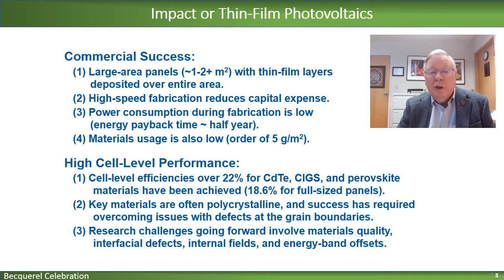At the cell level, we're talking about pretty high efficiencies. Over 22% has been achieved by cadmium telluride, by what we call CIGS, and by the class of perovskite materials. At the same time, in the field, we're approaching 19% at the full-size panel level. The key materials being used for thin film photovoltaics are often polycrystalline in nature, and the success of using these has meant overcoming various issues with defects, particularly at the grain boundaries within a polycrystalline solar cell. The research challenges going forward also involve the quality of the material, interfacial defects, internal fields, and the offsets of energy bands when we put two materials together.